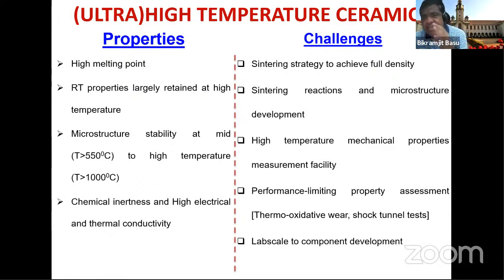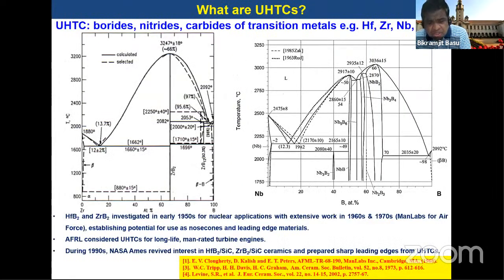Now, what are the challenges? The challenge is how to consolidate extremely dense sintered components with good strength reliability, as well as meeting other performance criteria. The reason is that various additives are added to these ultra high temperature ceramics during the consolidation process, and that leads to sintering reactions. I'll show you some examples of that. Then high temperature mechanical property measurement facilities often become a bottleneck, because many academic institutes do not have facilities where you can measure strength and other performance-limiting properties at temperatures above 1000 or 1500 degrees Celsius. UHTC is generally defined as a class of ceramic materials, particularly borides, nitrides, and carbides,